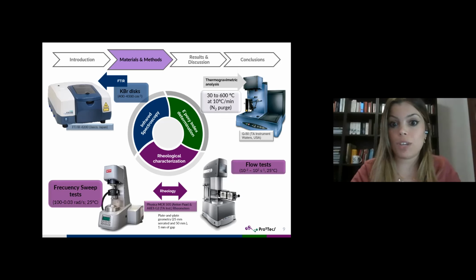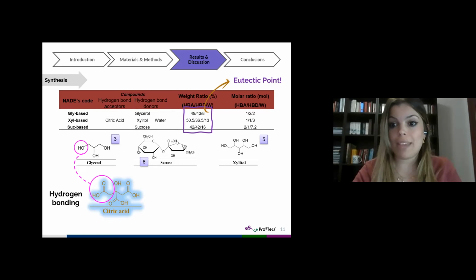As previously discussed, the synthesis of NADES was successfully carried out by mixing all the components according to the proportions that we can see in the table, achieving homogeneous mixtures at the eutectic point and stable at room temperature. In general, NADES structure is influenced by the different interactions occurring between carboxylic groups of citric acid and hydroxyl groups contained in the hydrogen bond donor compounds. And for that, different proportions of these compounds are required to attain this eutectic point, as you can see here